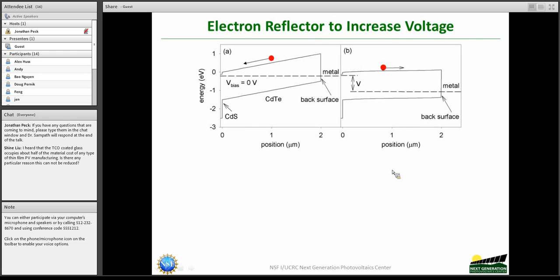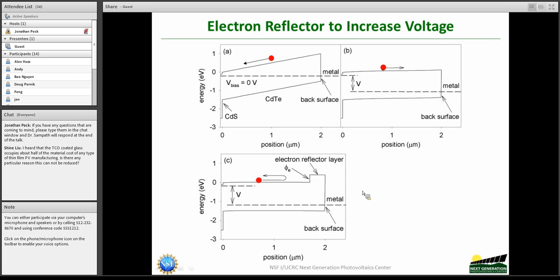And it is these large grains without intervening grain boundaries that lead to very good device performance. So here is the schematic for what we are trying to do at the back, having an electron reflector to increase the voltage. And the electron reflector is a higher band gap material at the back. And what that does is we ideally would like to create a barrier in the conduction band so that the minority carrier electrons can be reflected away.